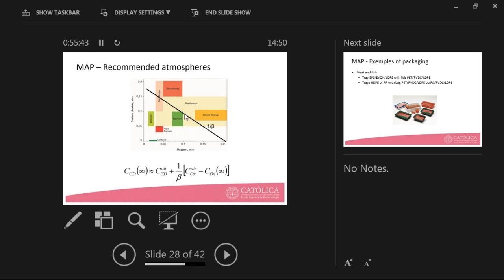We may use a specific material for a certain product when the line that I draw with the slope as the inverse of beta intersects the area where my product is located. For example, in this case shown in the slide, we may use the film material that corresponds to this line for mushrooms and for cantaloupe melon, but not for strawberries, not for spinach.